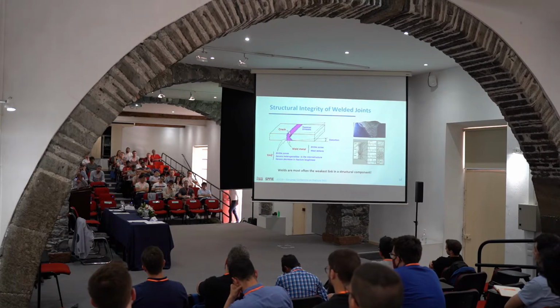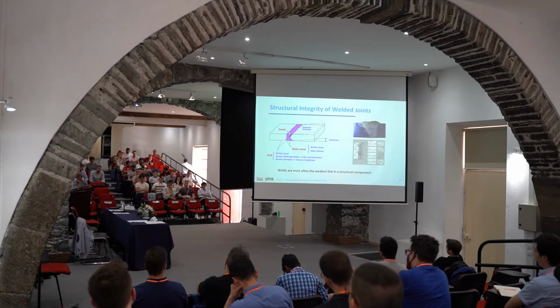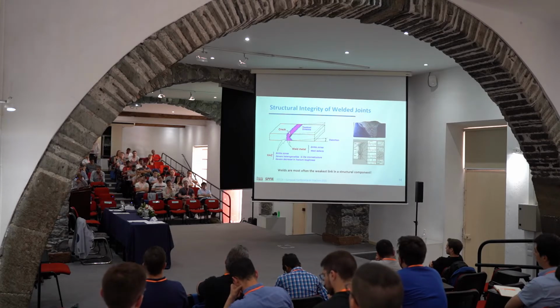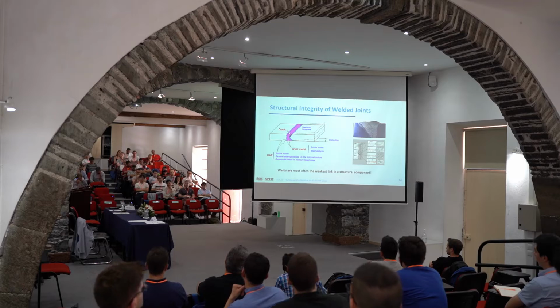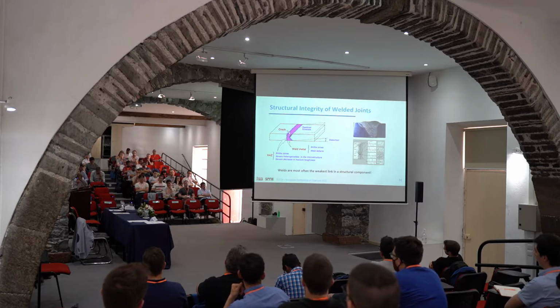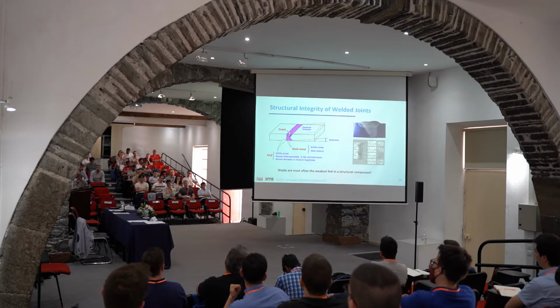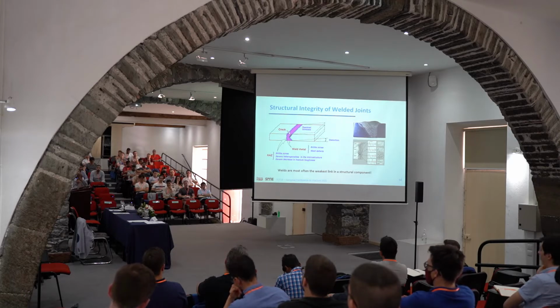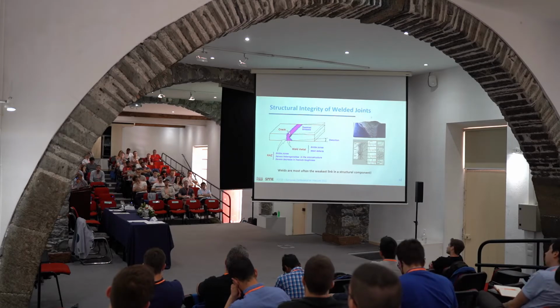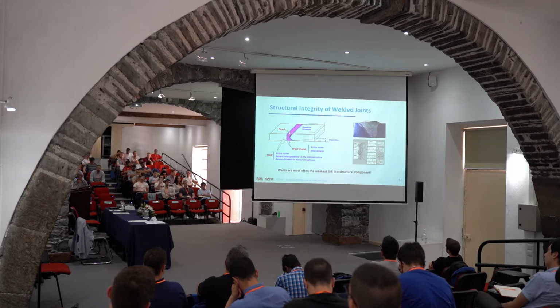But worse than that, after the welding, you need to do many passes. This is called the root pass, this is the reinforcement, and you usually have 10, 12, 15 passes depending on the thickness of the plate, either automatic or manual welding. The second pass, the third pass, will reheat what was already transformed. So you have a very complex phase transformation here.